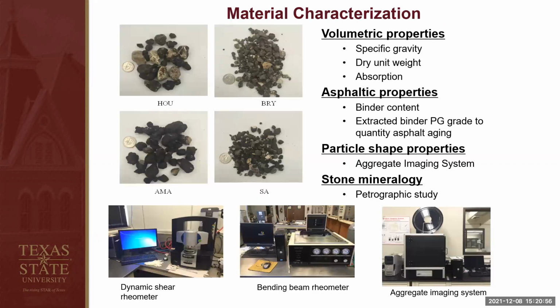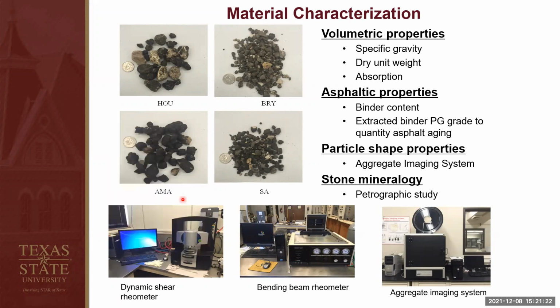So for our project, the TxDOT funded project, we collected a lot of RAP from different districts in Texas. So here I'm showing 4 RAP samples were collected. One is from Houston and from Amarillo. Those 2 RAPs, as you can see, let me bring my pointer here. As you can see, Houston and Amarillo RAP, they contain bigger aggregate size compared to the other 2 sources we selected, Bryan and San Antonio. They contain mostly intermediate particle size. The gradation of the RAP plays a significant role in our research, as I will show you guys later.